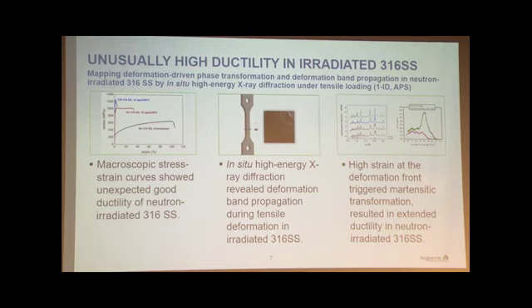So we realize the deformation is not happening uniformly like in the non-irradiated material. The deformation actually happens at one end of the specimen and then starts to sweep across the gauge. And once the deformation band propagates, it actually triggers the phase transformation. So austenite actually becomes martensite. And we know martensite is very hard. That's why the material doesn't have this typical early onset of plastic instability. That's why this material has much longer elongation. So when we talk about advanced material, we often don't think about 316.